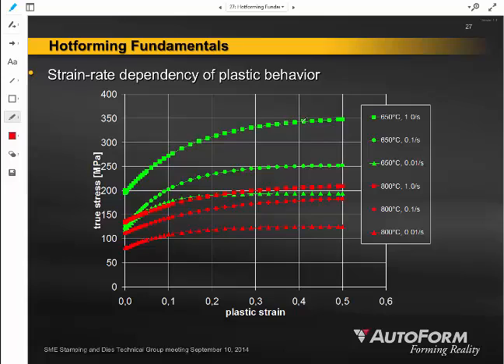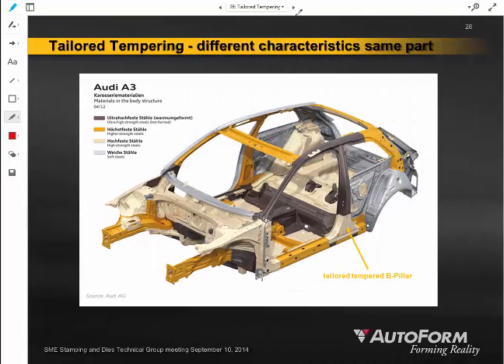We also have to know not only how the different temperatures behave, but material also has different strain rates. The faster it stretches compared to being stretched slowly, we do see different characteristics between the stress of the material and its strain, and therefore another complexity of our forming operation in order to mathematically model it.